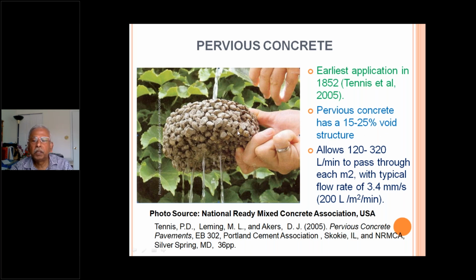It can have 15 to 25% void structure, and it allows 120 to 320 liters per minute to pass through each square meter, with a typical flow rate of 3.4 millimeter per second. That is equivalent to 200 liters per square meter per minute.